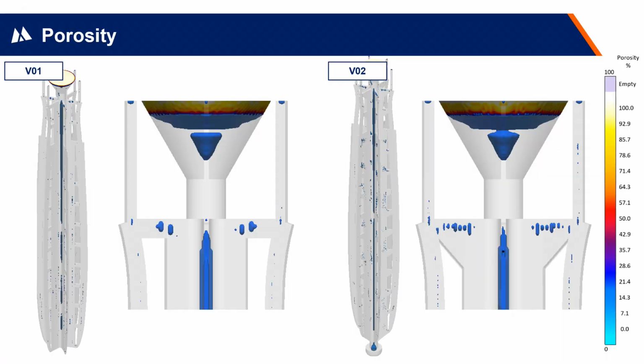At the same time, we began work on our material selection process to determine what alloy to use for the blade. The selection process maximizes hardness, yield strength, and toughness, which will give our blade a sharp edge, allow it to bend before breaking, and reduce the potential of cracking. This is incredibly important because cast parts contain voids that act as crack initiation sites. The material we selected for our sword is 17-4 stainless steel, which has the added advantage of tunable hardness.